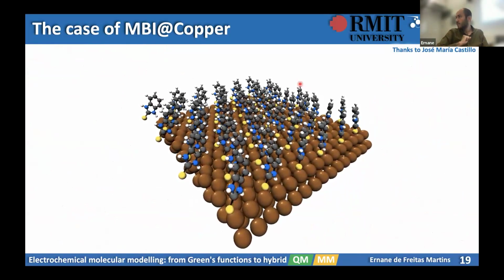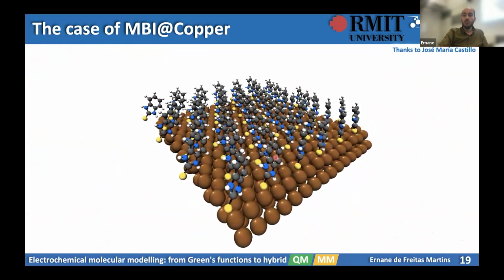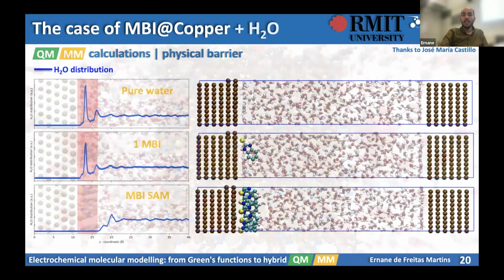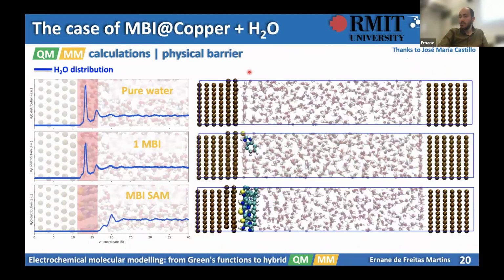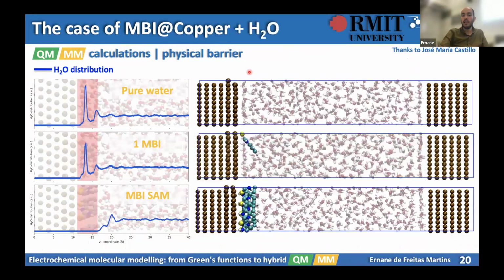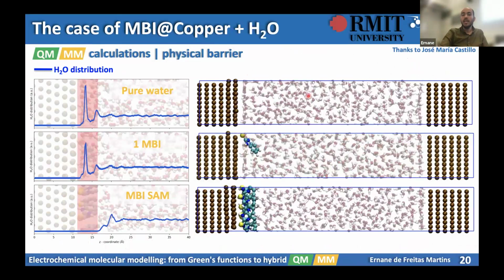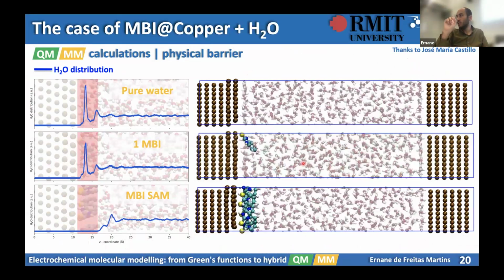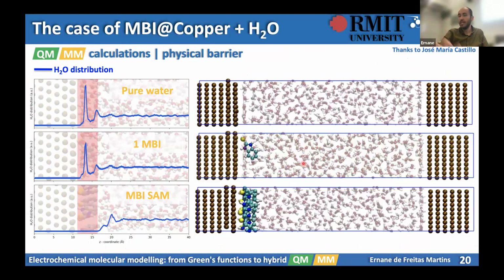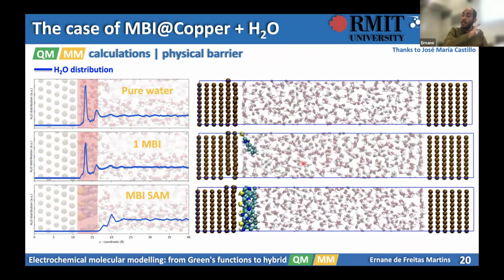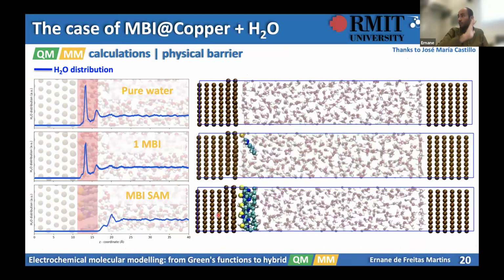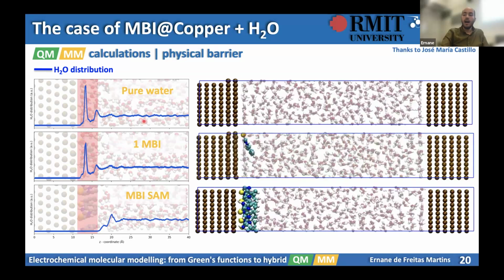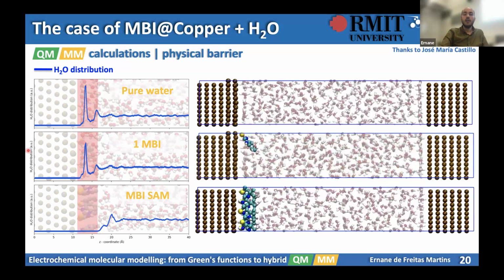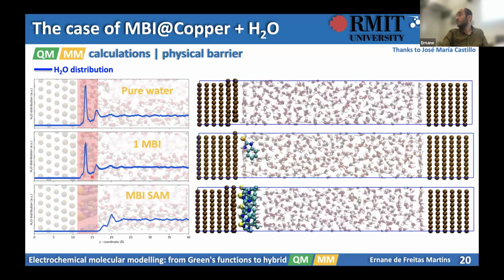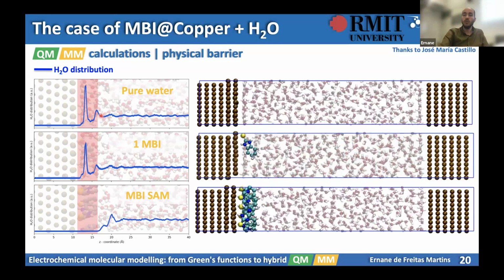What can we extract from here? If we go to this case here, Jose Maria selected 3 case systems. One is without the inhibitor molecule, this above one. The middle one is the case with a single inhibitor, that means low coverage. And the third one is the case with a self-assembled monolayer, so full coverage. And here on the left are the water distributions as a function of Z. Same kind of plot I showed before.